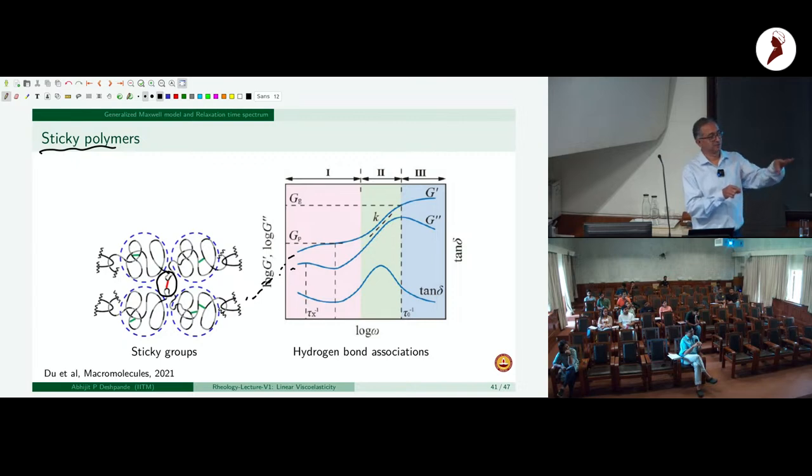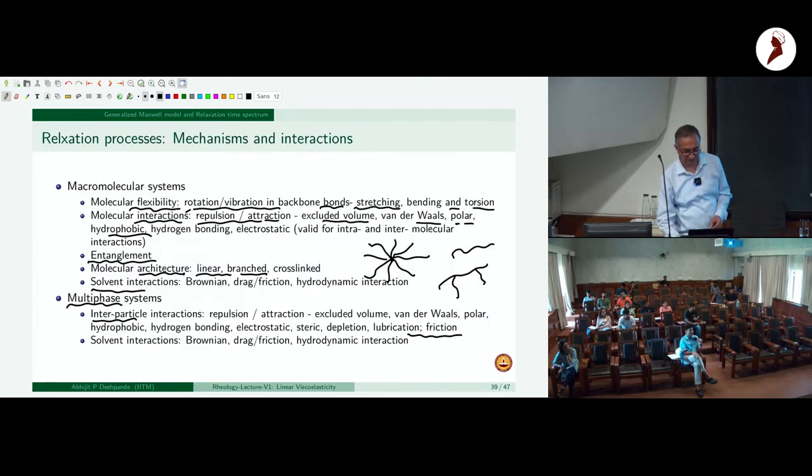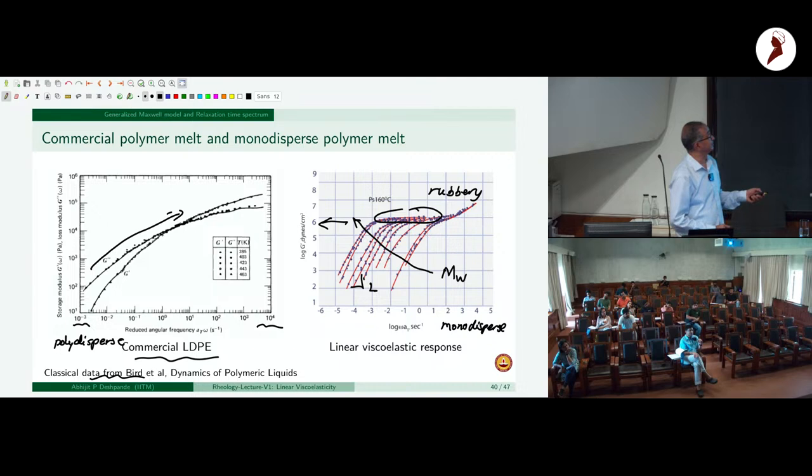The monomers are attached together with covalent bonds. So the conformational landscape of a monomer is restricted by the fact that its two neighbors are fixed, neighbors on both sides. But Brownian motion of the chains, yes. That's why this kind of behavior is an indicator of the fact that at some time scales, the entanglement points are acting as if they are cross-linked points, which at this time scale appear to be permanent. Beyond this, the subsegmental modes are relevant, and therefore entanglement points are not relevant. And at much higher time scales, or lower frequency, the chain can reptate out.